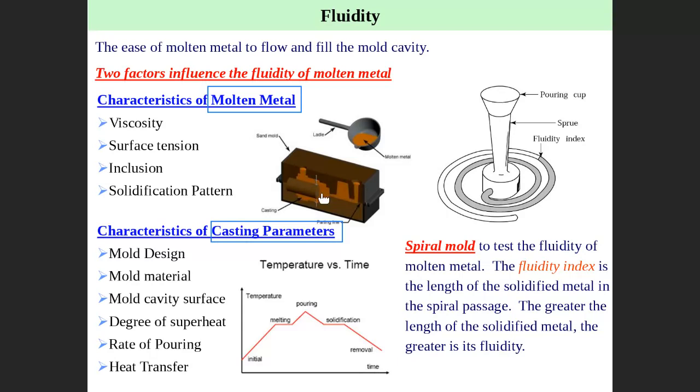Mold design is very important, because mold design means this kind of runner, sprue, runner and so on, and riser. This also affects the fluidity. If you make smaller channels, then fluidity becomes lower. You need a bigger channel to allow material to flow easily and fill all the cavity, otherwise fluidity is getting less.